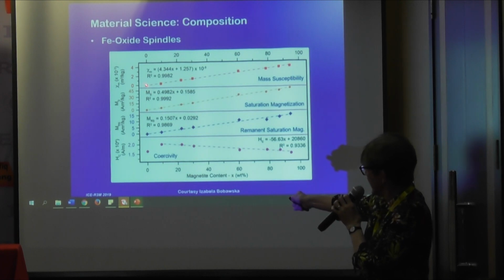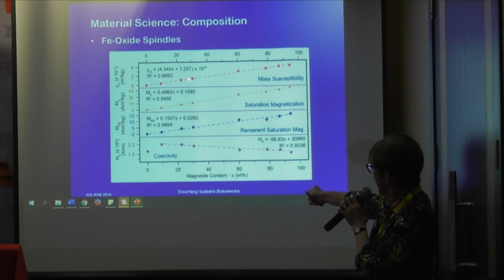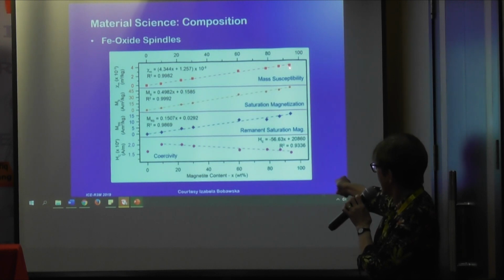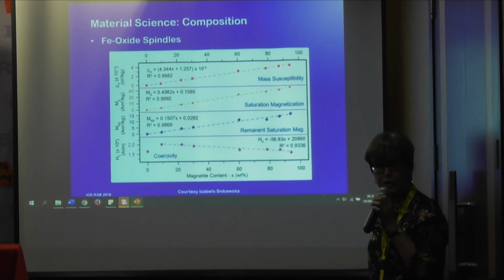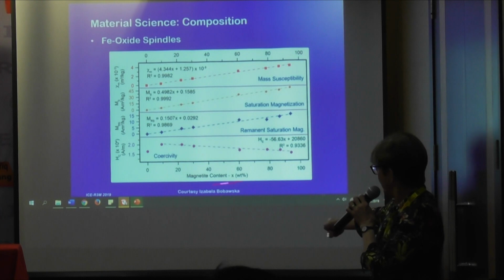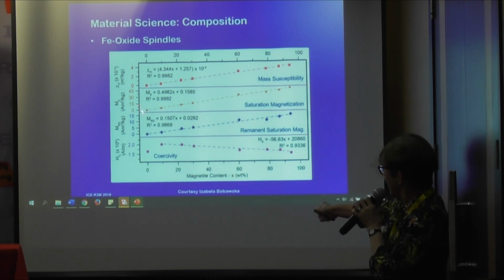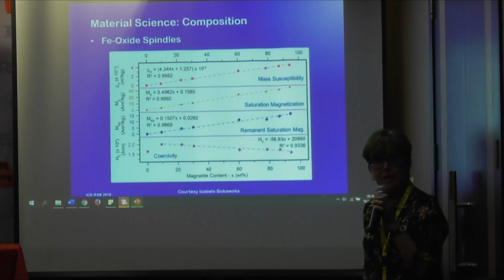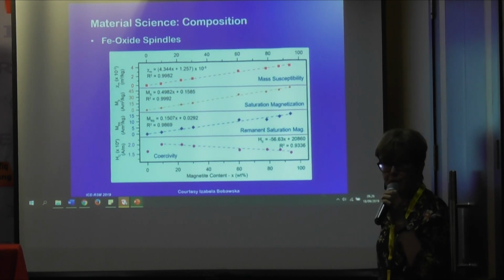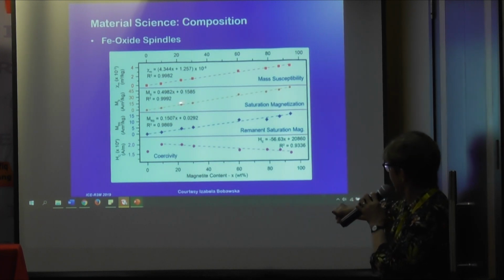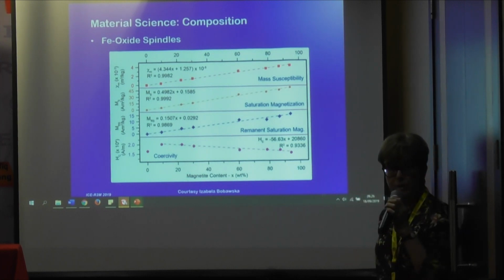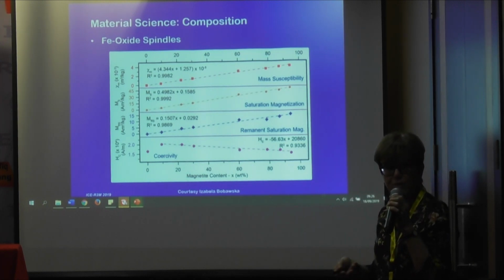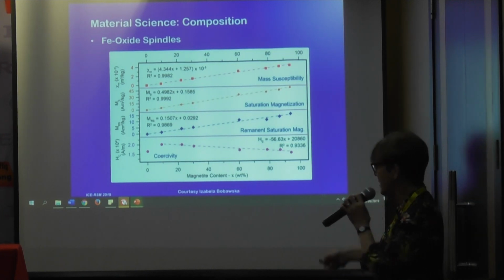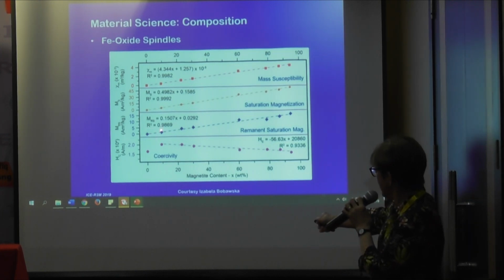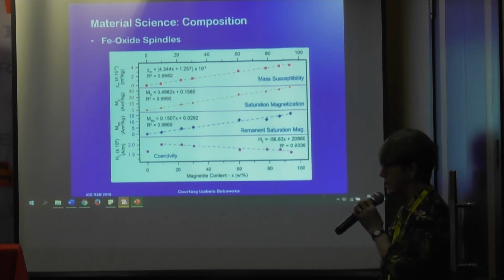The starting one has a very low susceptibility, and as they reduced the sample, it got higher and higher. So they got a nice linear relationship for the amount of magnetite or maghemite and the susceptibility. The same is for the saturation magnetization. So again, you can see that they got a steady linear increase in the saturation magnetization as they converted the hematite to magnetite maghemite. The same for the remnant saturation, a nice linear increase.